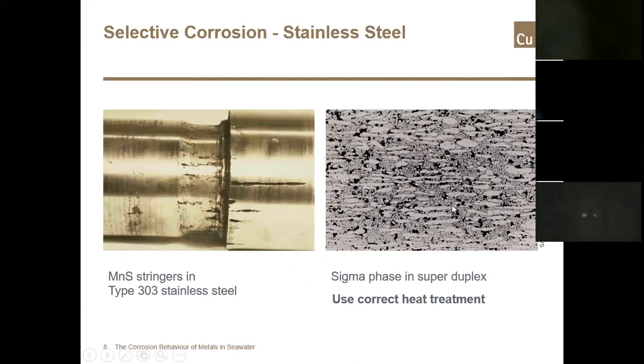On the right is a microstructure of a super duplex stainless steel, which is a more complex stainless grade that should theoretically offer much better corrosion resistance than more standard, cheaper grades of stainless. However, on this occasion, the material has been heat treated incorrectly, and the alloy has created a sigma phase that preferentially corrodes in seawater. So again, it shows the importance of selecting the correct material and taking into account all the material aspects.